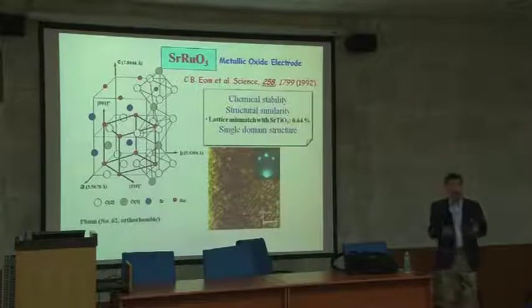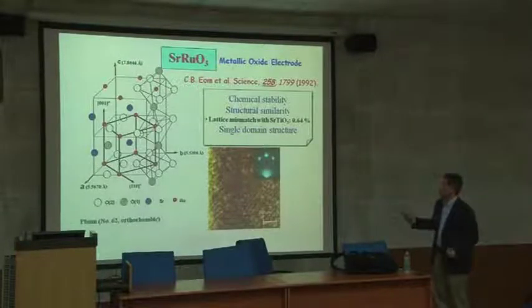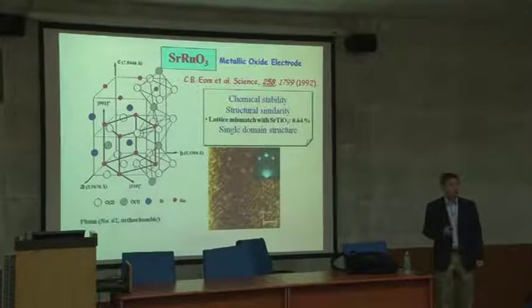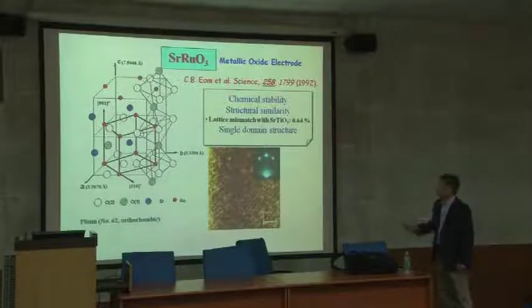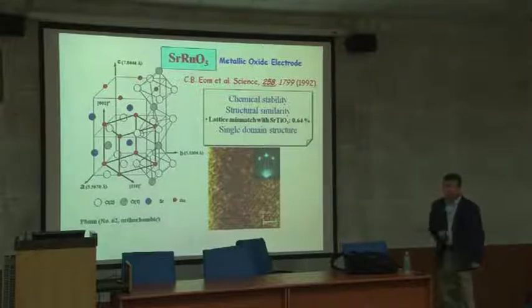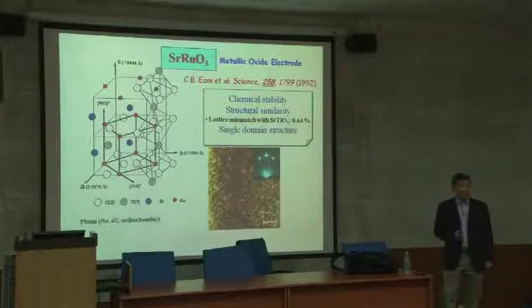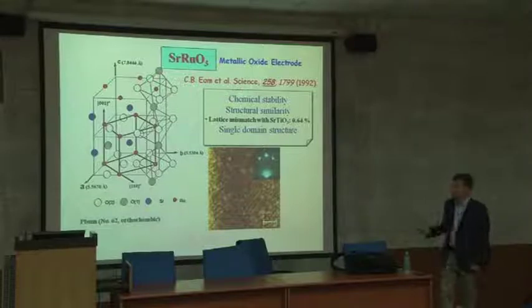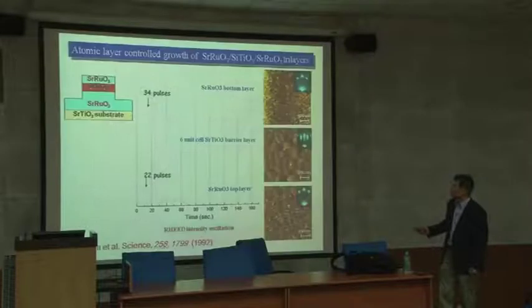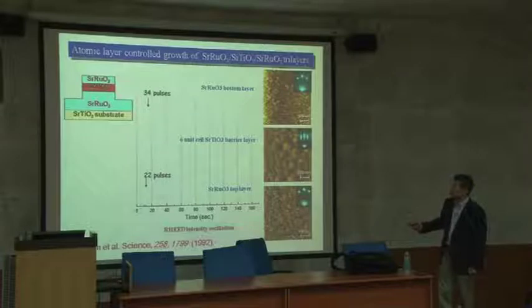And doing so, you actually grow this strontium ruthenate. It's another perovskite, a very interesting perovskite. It's basically an itinerant ferromagnet and also a spin-polarized ferromagnet. And then this material was grown on this substrate. And then I just want to show you real-time imaging of strontium ruthenate and strontium titanate and strontium